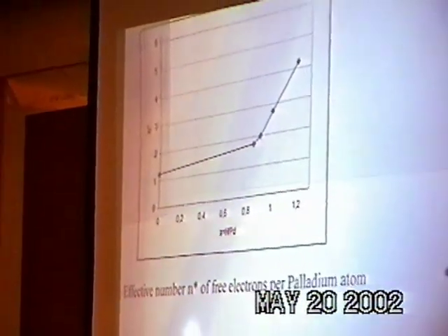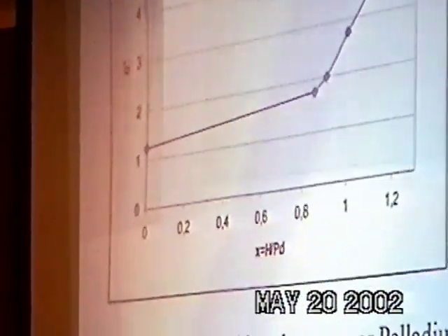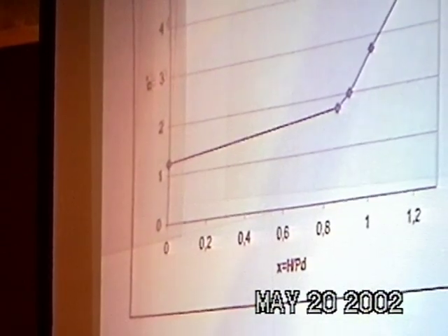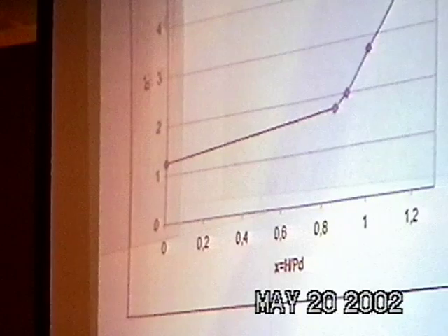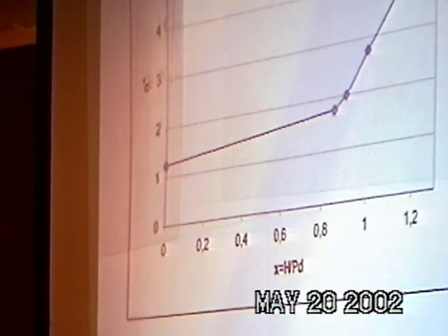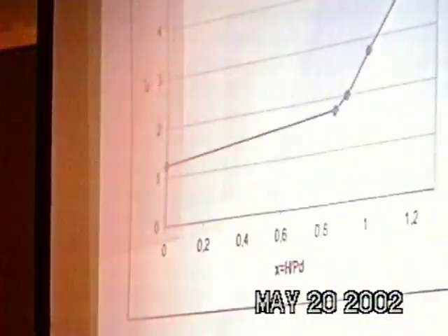Okay, you can see in this graph represented as a function of x the number of carriers of the current as measured by the Hall effect. And you can see that there is just a discontinuity point at about x equal 0.8. Since in the paper it is not defined what was the temperature of the experiment, maybe this 0.8 will be just the beta gamma transition. I don't know, because we are used to consider 0.7 the transition point. Here is 0.8. But the paper, which is a short letter, actually is not very clear about it. In any case, there is a discontinuity point where the slope of this behavior changes abruptly.